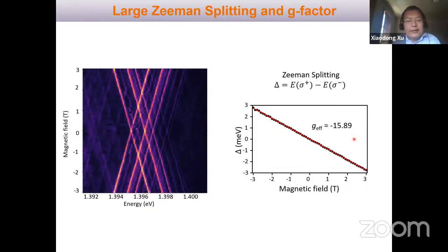But what is consistent is that the g factor seems to be determined only by the twist angle, and with narrow lines, the g factor is consistent with free 2D excitons. Because the g factor is determined by the crystal lattice, this shows that the exciton is trapped by the Moiré potential, while its g factor is still determined by the crystal lattice.